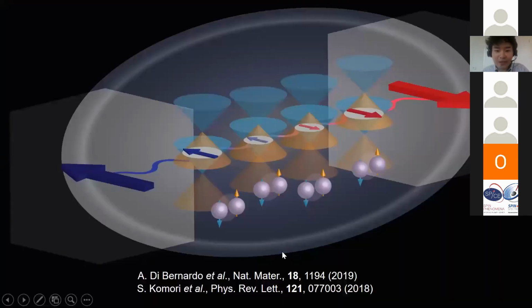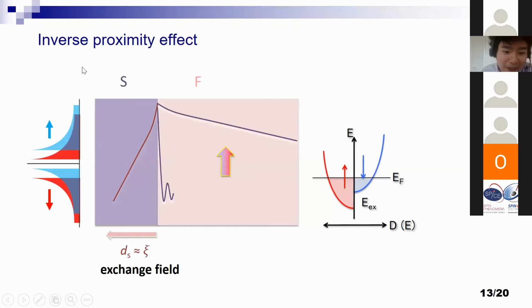And as a second part, I would like to also talk about oxide SF interface proximity coupling. This is mainly the results I got with Dr. Angelo Di Bernardo. Angelo and I have tried many combinations of SF materials. And we mainly focused on the penetration of magnetic order inside a D-wave superconductor, which we call an inverse proximity effect. So inversely, magnetic order can penetrate into a superconductor. And that can spin split the quasi-particle density of states and suppress Tc of the superconductor. And this length scale is typically around the coherence length of a superconductor.